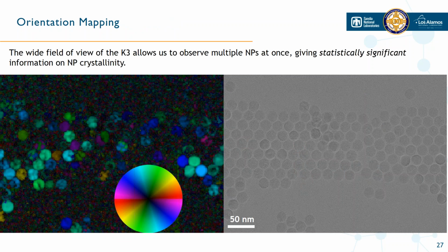So this is another Python script that Ben from Gatan actually wrote up, and here he's implemented this color wheel. If you look in the FFT for the presence of a spot, say the 100 spots over here, then these are going to be shown as blue, and likewise green and red and yellow around this color wheel. So now we can start to see the way that these particles are oriented in relation to each other, which for magnetic nanoparticles is really important,